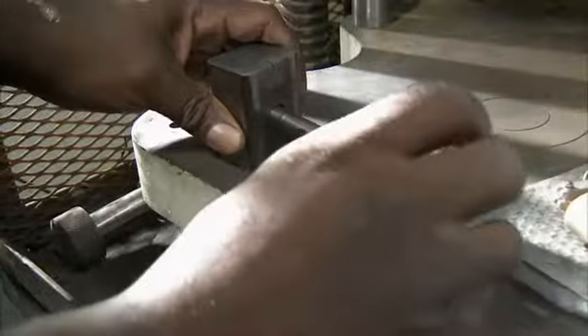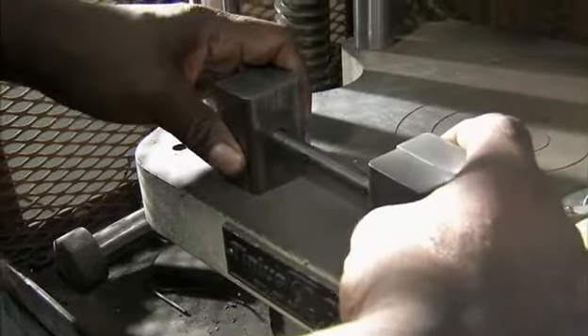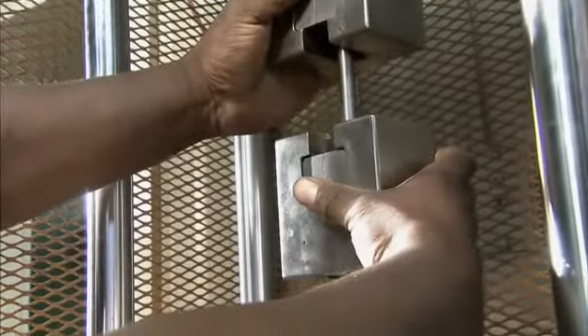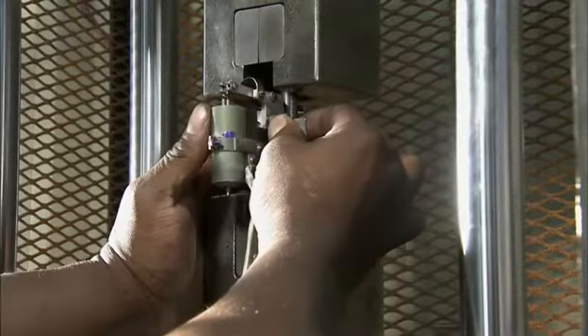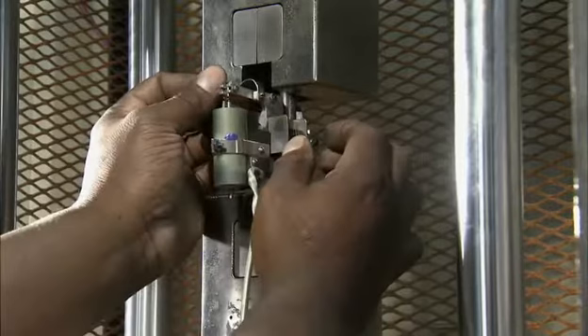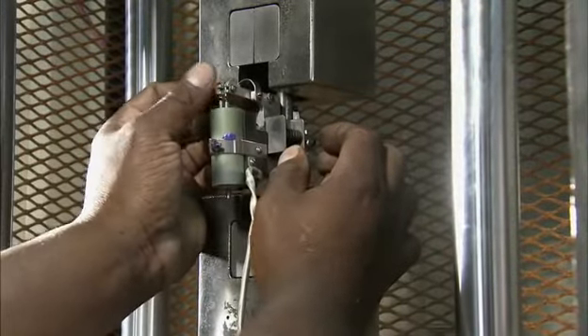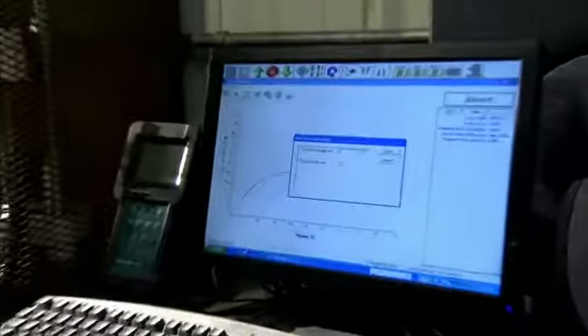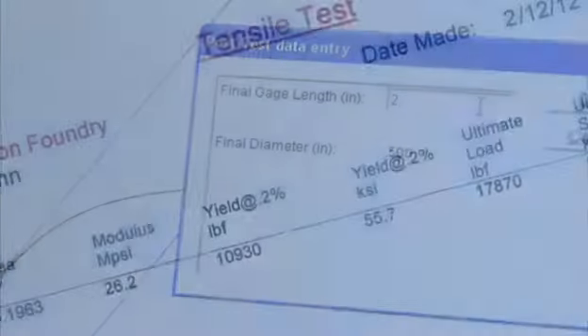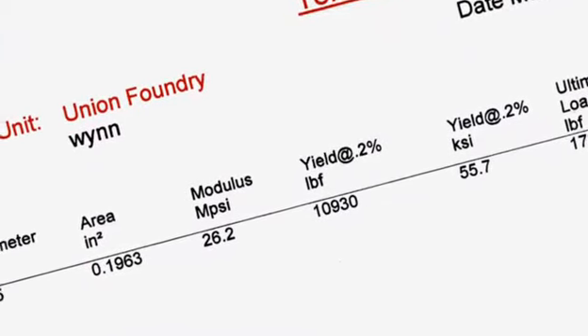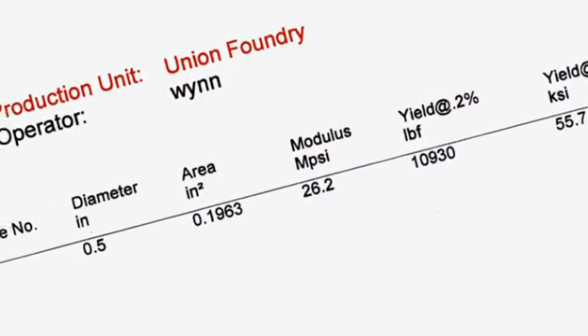In addition to these samples, a test bar is poured every 3 hours during production. The test bar is machined to a specified length and diameter to meet AWWA testing specifications. The bar is then placed under tensile stress until it fails. Readings are automatically taken, which are used to determine the tensile strength, yield strength, and elongation properties of the iron.